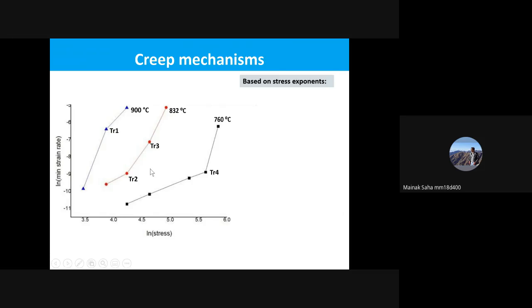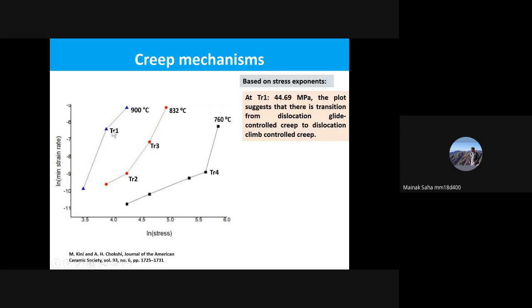So what we can find out is that TR1, the first transition stress, is equal to 44.69 MPa. This can easily be found when we extrapolate this data and take the logarithm. The plot suggests that there is a transition from dislocation glide control creep to dislocation climb control creep. Similarly, for the second case, at around 832 degrees, we find that the transition stress is slightly higher, 66.68 MPa, where there's a transition from dislocation glide control creep to dislocation climb.